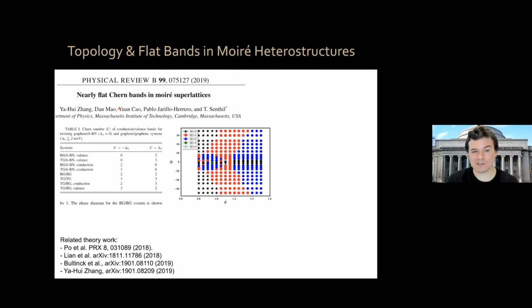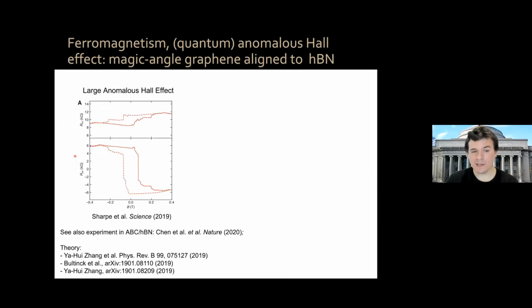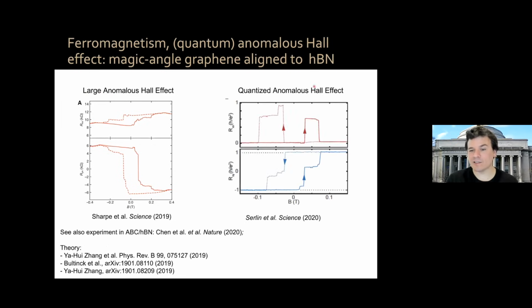In fact, soon after our discovery, together with our theory colleagues, we predicted that there would be nearly flat Chern bands, meaning topological quantum anomalous Hall physics, in a variety of Moiré systems. Okay, a few months later, this was realized by the group of David Goldhaber-Gordon, who showed that there was ferromagnetism, showing here a large anomalous Hall effect in magic angle graphene aligned to hexagonal boron nitride. A few months later, the group of Andrea Young showed that there was this quantized anomalous Hall effect in a beautiful experiment. The group of Feng Wang at Berkeley showed that a different Moiré heterostructure, ABC trilayer aligned to HBN, also exhibits a very similar type of quantization. And by now we have many systems that do this. Okay.